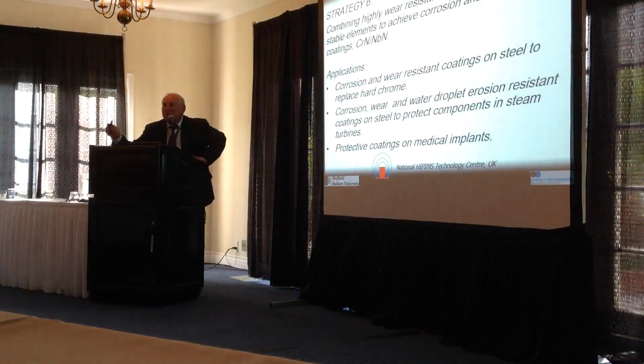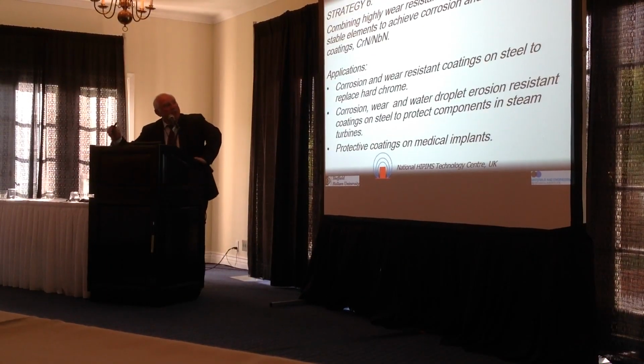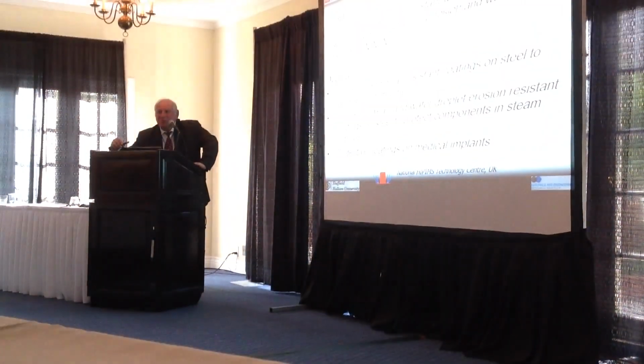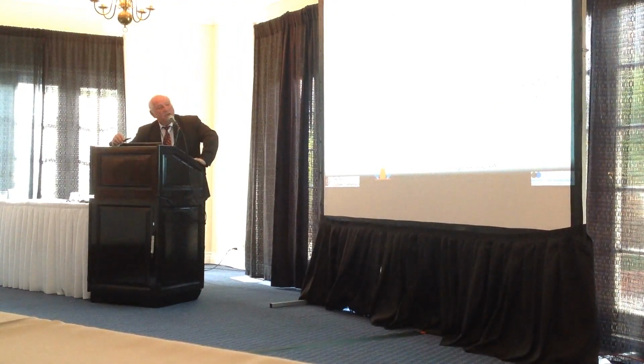And I'm with the last strategy, where we used highly electrochemically stable metals like niobium combined with chromium as a wear-resistant material to produce wear-resistant and electrochemically stable corrosion-resistant coating. So this work was carried out in an attempt to replace hard chrome. So this was the idea. And we have three very interesting applications with this coating.